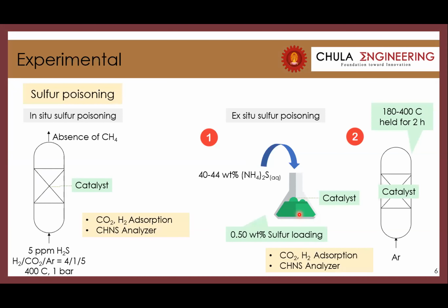The experiment on sulfur poisoning is divided into two parts. The first part is in situ sulfur poisoning: co-feeding 5 ppm of hydrogen sulfide with hydrogen, carbon dioxide and argon respectively through the fixed bed reactor until the absence of methane, and then taking the catalyst to test carbon dioxide and hydrogen adsorption, and CHNS analysis. The second part is ex situ sulfur poisoning, achieved by wet impregnation of ammonium sulfide on the catalyst, and then pressing, sieving, activating and aging, and working with argon to study the effect of catalytic performance dependent on temperature, and also taking the catalyst to test carbon dioxide and hydrogen adsorption, and CHNS analysis.